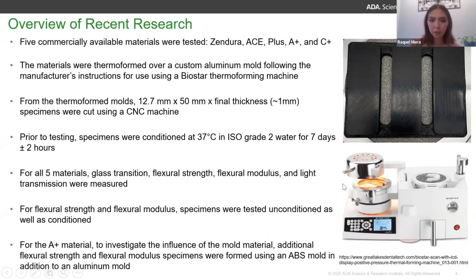For all 5 materials, we measured the glass transition, flexural strength, flexural modulus, and light transmission. For flexural strength and flexural modulus, we tested specimens unconditioned as well as conditioned. And for the A+ material in particular, we wanted to investigate the influence of mold material, so we tested flexural strength and modulus using an ABS mold in addition to our aluminum mold.